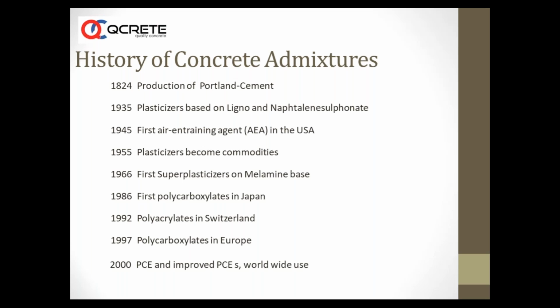In early 1935, plasticizers like ligno-based and naphthalene formaldehyde-based superplasticizers came into existence with limited water reduction. Around the same time, one of the first patents was done on SNF, sulfonated naphthalene formaldehyde-based admixture. The next step was in 1945, where air entraining admixtures came into being. That is said to be one of the biggest changes in the history of concrete, which boosted concrete practices significantly and changed them forever.